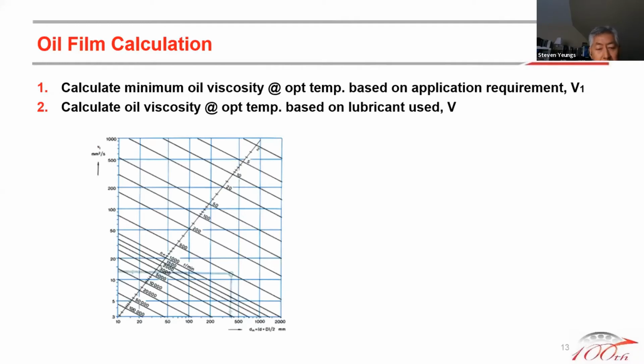Here's a diagram that we can make use of to calculate the so-called minimum required viscosity based on the application requirements. On the bottom, we have the size of the bearing. In this case, the mean diameter is 53. And then the slanted lines are the speed of the bearing. So basically, we just draw a line vertically up and hit 7,800, and then go across horizontally. It tells me that for this application, at 7,800 RPM, I need a minimum of 7 centistokes at the operating temperature, in this case 55 degrees Celsius.